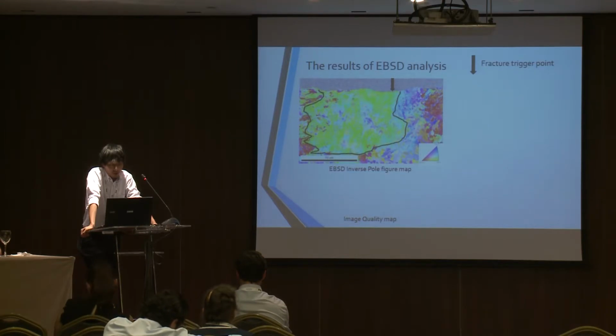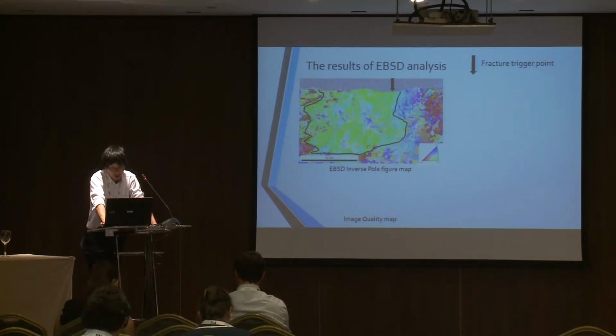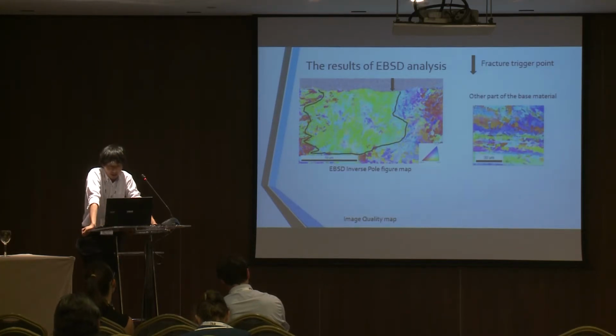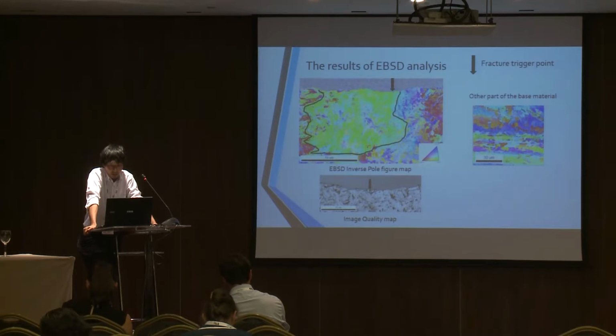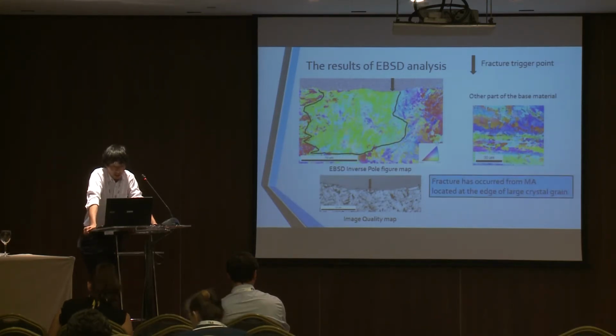This figure is an inverse pole figure map near the fracture trigger point acquired by EBSD. The portion of the black arrow is the brittle fracture trigger point. Compared with the other part of the base material, this grain size seems extremely large. The IQ map shows the sharpness of the orientation, and the portion where the direction cannot be read clearly is displayed in black. The MA, which is a brittle fracture trigger point, cannot clearly read the orientation because of its high carbon concentration and high dislocation density. Therefore, the position of MA at the fracture trigger point could be identified. In summary, fracture has occurred from MA located at the edge of the large crystal grain.